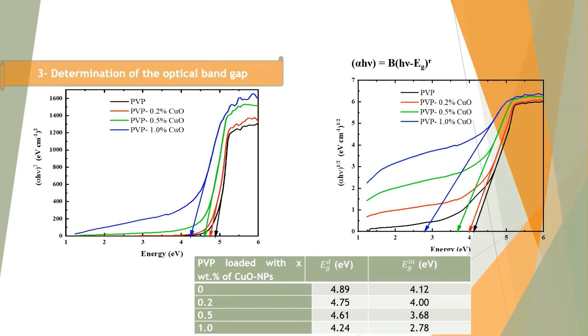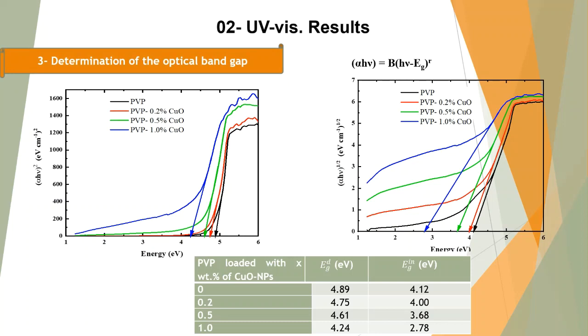We determined the values of the direct and indirect optical band gap energy using the equation. As we can see from this figure, the variation of alpha h nu to the power 2 and alpha h nu to the power half with the incident photon energy shows only one absorption shoulder, which means that all the samples have only one absorption peak. Extrapolation of the linear portion of all curves to the x-axis gives the energy values of the prepared samples. As we can see from this table, increasing the copper oxide concentration results in a decrease in the direct and indirect allowed optical band gap energies.